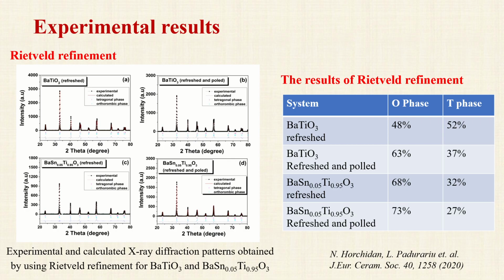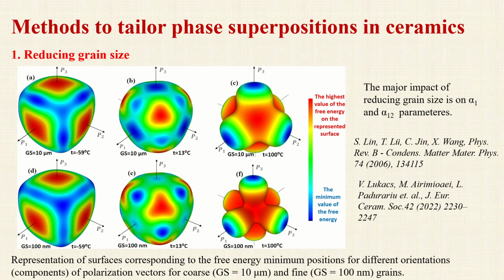These two experimental cases were a good start in confirmation of the hypothesis regarding phase superpositions and their impact on ceramic properties. In the following, I would like to present other more recent results regarding the possibility to adjust further the phase superpositions in barium titanate-based ceramics. For example, it was reported in literature that the reduction of grain size modifies the alpha-1 and alpha-1,2 parameters, which significantly change the diagrams of the free energy.